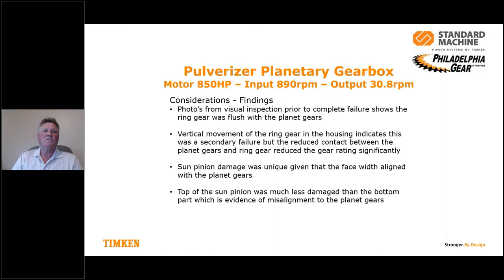Photos from the visual inspection, prior to us getting the gearbox, showed that the ring gear had not moved out of position. It was still flush with the planet gears. That told us that the movement of the ring gear was really a secondary failure, not a primary failure. The sun pinion damage was very unique: the face width was aligned with the planet gears, but it was really damaged. The top of the sun pinion was much less damaged than the bottom, which is evidence of misalignment.